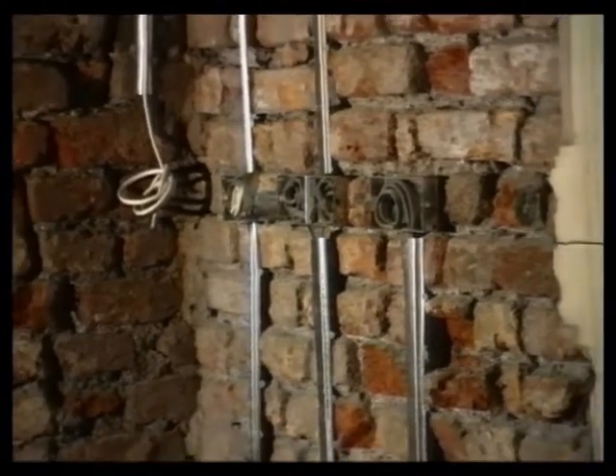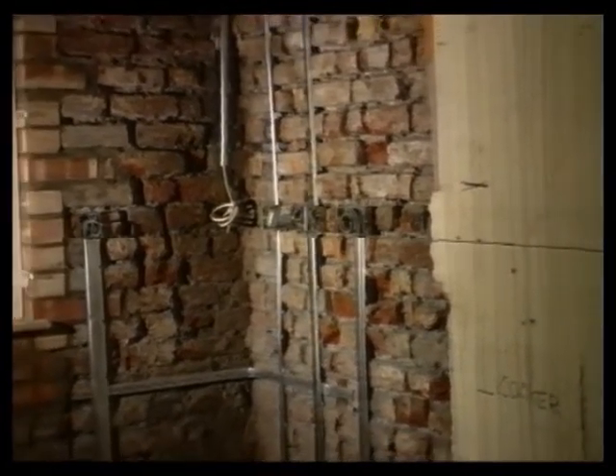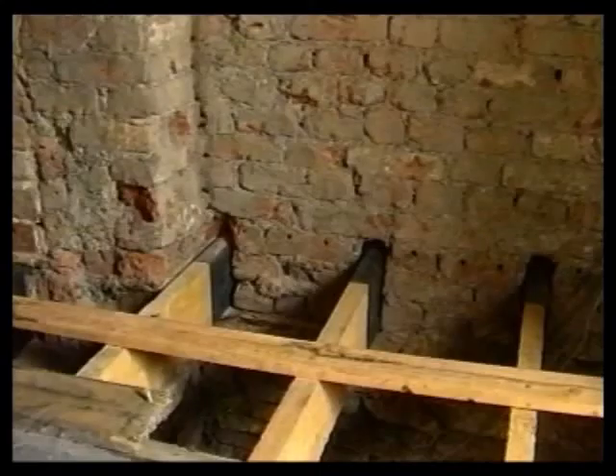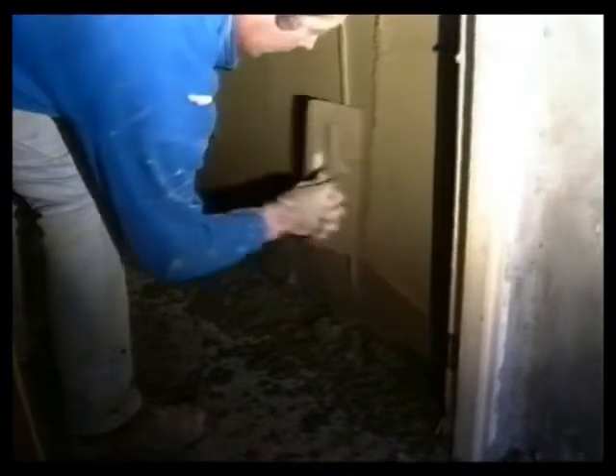These old damp walls contain chlorides and nitrates absorbed from the ground. Eventually, these chemicals, known as hygroscopic salts, will migrate to the plaster surface. They absorb moisture from the air, resulting in damp patches on the face of the plaster. Most gypsum plasters can't prevent this surface migration, and in damp conditions, or where a DPC has been installed,